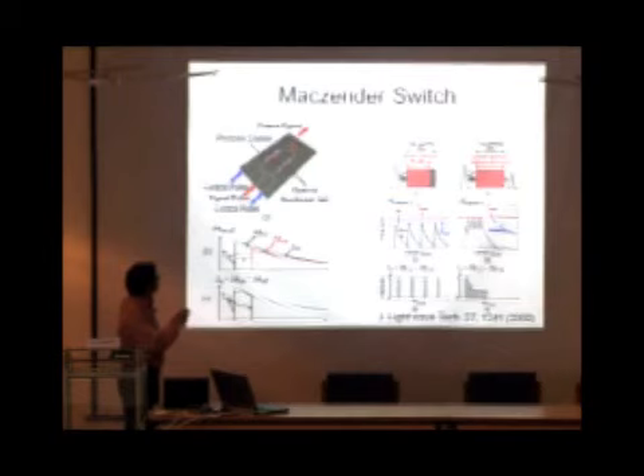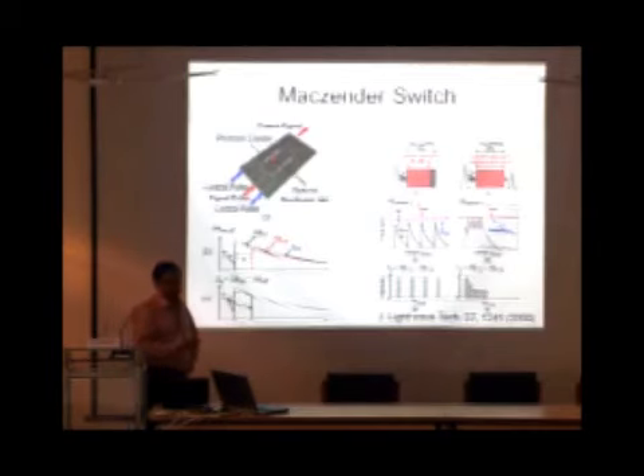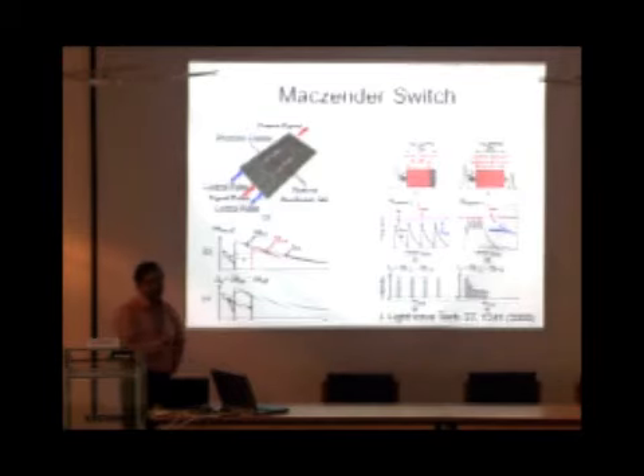Now if you use a control pulse to change the refractive index, for example in this reference they have used quantum dots. By using the control pulse, you can control the absorption of the quantum dots, which changes your saturable absorption. You control that, so you are changing the refractive index of one of the paths, which changes the phase of one component with respect to the other.